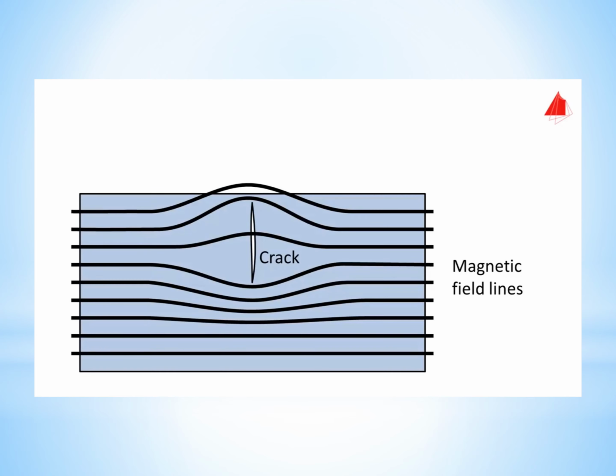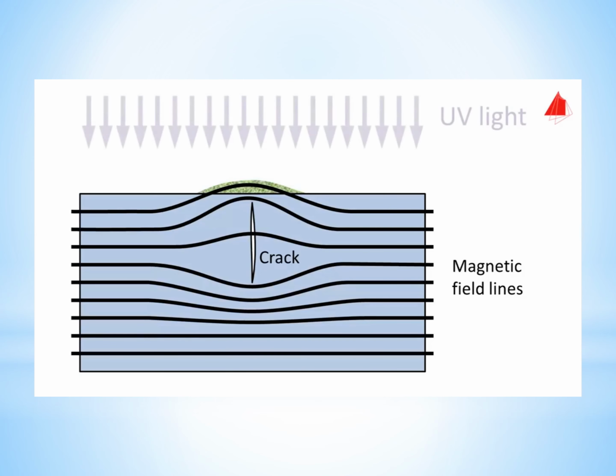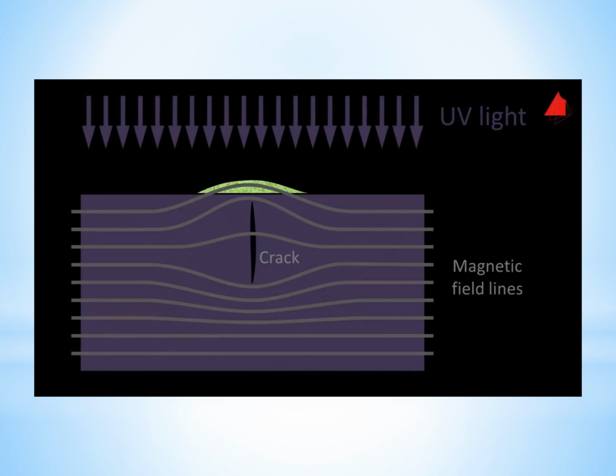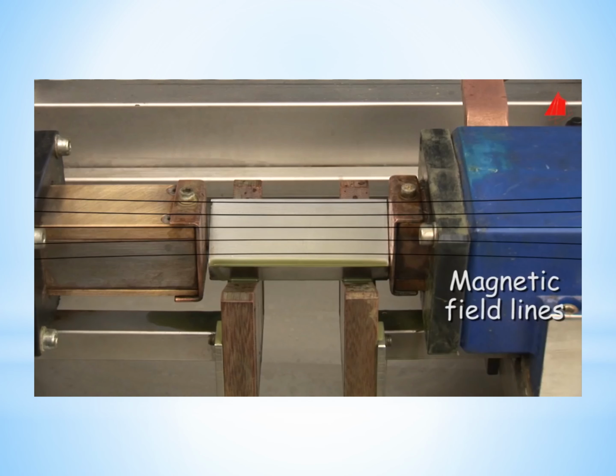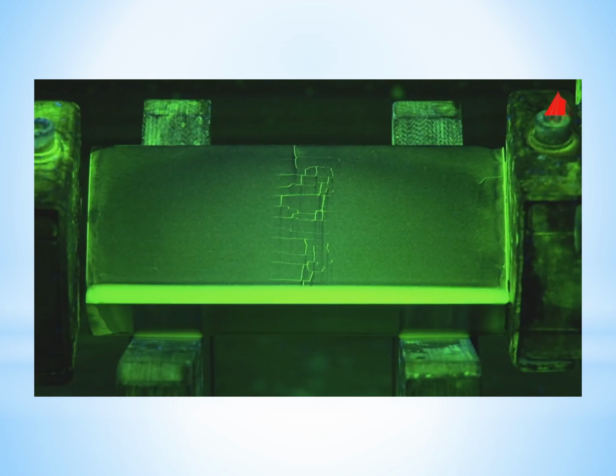Even cracks can be detected that are not open to the surface but just below it, as long as they are not too far below the surface. But one precondition must always be fulfilled. The magnetic field lines must be perpendicular, or at least at a certain angle to the defect. Otherwise there will be no leakage field and the defects remain undetected. Our test sample has been magnetized in horizontal direction. The magnetic field lines run horizontally. This is the reason why cracks in vertical direction are visible particularly well.